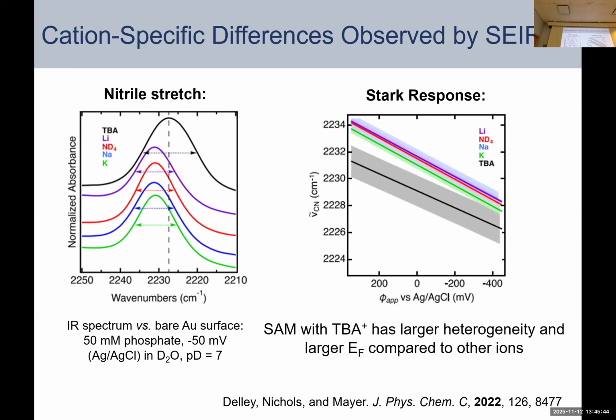Okay, looking at the nitrile, because remember it's a mixed SAM, so we have two different vibrational probes on this surface. You can see again that tetrabutyl ammonium is an outlier, and really all the rest of them behave in a very similar way. So here are the Stark responses. This is showing you how, as a function of applied potential, the wavenumber changes. So the slope here and the y-intercept is reflective of the local electric field, or at least it scales with the local field. And based on this difference for tetrabutyl ammonium, you can see that the tetrabutyl ammonium cation is not really able to penetrate as well into the self-assembled monolayer. And so we're seeing larger local electric fields with that cation specifically.